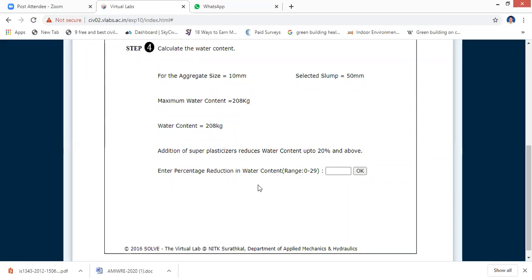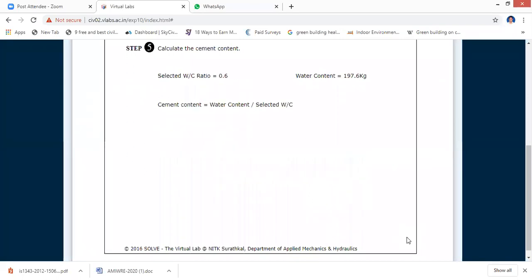To reduce the water cement ratio and increase the workability, you can add superplasticizers into it, up to 20% and above. So you can select a range between 0 and 29. Okay, so enter the percentage reduction in water content. I am selecting around 5%. I want to add 5% of superplasticizers, which improves the workability and reduces the water cement ratio. Okay, so the maximum water content is 197. See, the water content earlier without any admixture is 208. By adding superplasticizer into concrete, the water content was reduced to 197. Right? And then cement content. The cement content will be calculated from the water content and the selected water cement ratio.